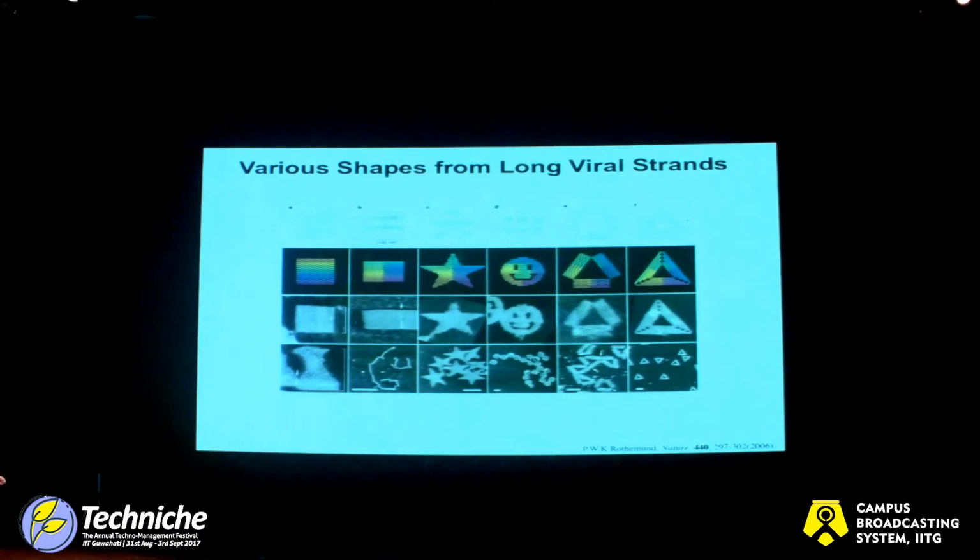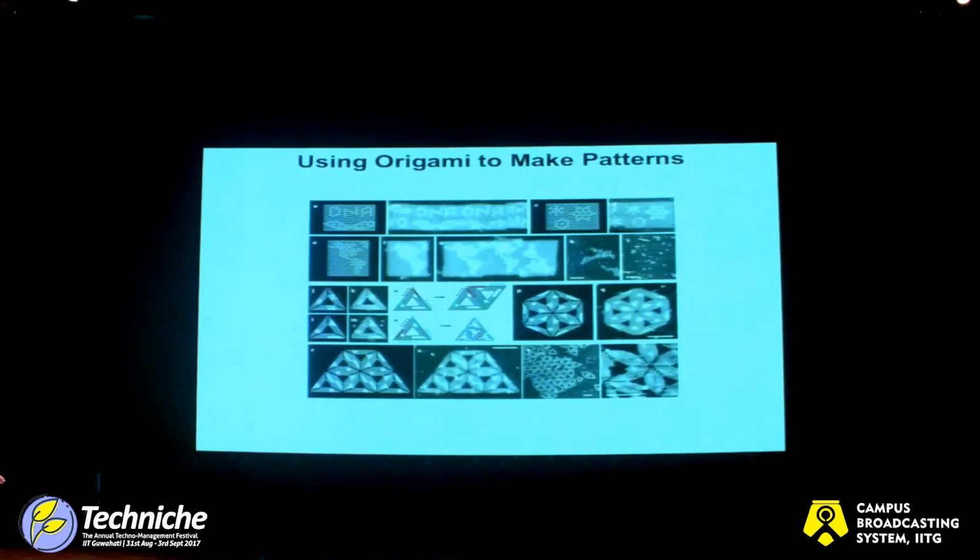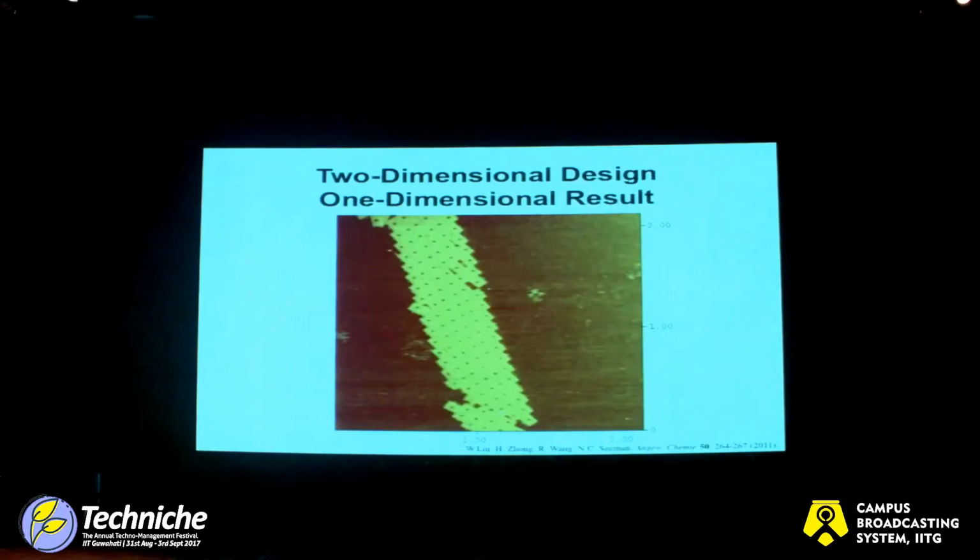The important thing about DNA origami is not that you can make a smiley face. The important thing is that in an area of roughly 9,000 square nanometers, if we're going to restrict ourselves to 2D, we have about 200 addressable points. So for example, here is his schematic, and this is the actual construct that he made. This is the Western Hemisphere that he was able to draw with his patterning, the same way we made the stripes. So here's South America, here's North America, there's Greenland. You can recognize the whole thing.